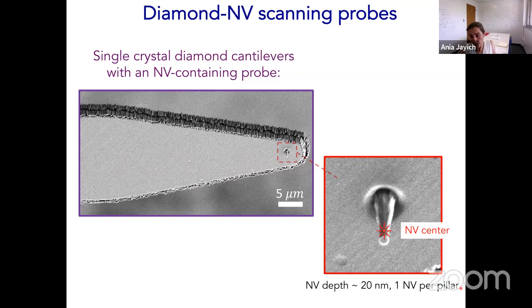And so not every probe has exactly one NV center, but we have a statistical probability for there to be one NV center per probe. We set the depth here to be about 20 nanometers. NVs are about 20 nanometers below the surface. Again, because of this interface-induced decoherence, that's what we've been engineering. And one of the future goals is to get these NVs even more shallow while still retaining coherence.